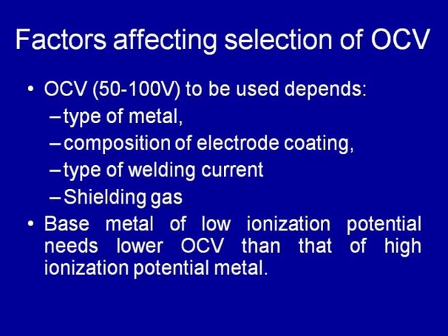Similarly, for the type of welding current, DC current requires a lower open circuit voltage than AC current, because in case of DC, once the arc is ignited, the current magnitude and its direction remain unchanged and a smooth and continuous flow is maintained easily, while in case of AC, the magnitude of the current and its direction continuously change in every half cycle, and that is why the arc has a tendency to get extinguished, especially when the current is 0. That is why to reignite the arc, it is necessary that the open circuit voltage is higher than that used while welding with DC.